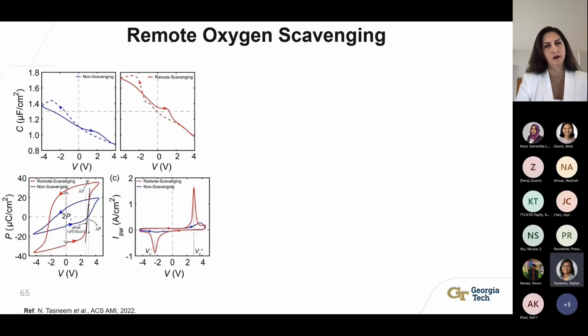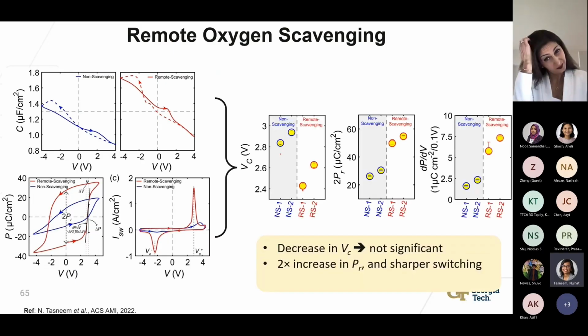So we also measured the electrical characteristics of these two samples. And we saw that the write voltage of the scavenged sample decreases, which is expected since the interfacial layer thickness is decreasing. However, the decrease in the write voltage is not as significant as we expected. It decreases only by 10%. At the same time, the scavenged sample showed higher 2Pr and sharper switching than the conventional non-scavenging sample. So these results were published in ACS AMI in 2022.